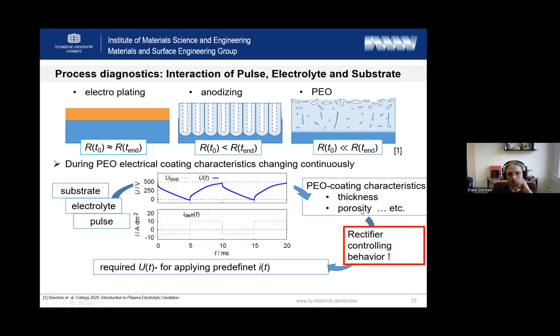And so the thickness, porosity, and resistance of the coating influence the voltage signal which you need for applying the predefined current signal. And that's why you can get a current signal which is completely different to what you initially applied. And it's not a mistake of your rectifier. Our rectifier is working quite well, making really pretty rectangular pulses in non-passivating systems, or when we apply electrically conductive coatings. But if you apply PEO coatings, you have a complicated interaction of all these parameters.